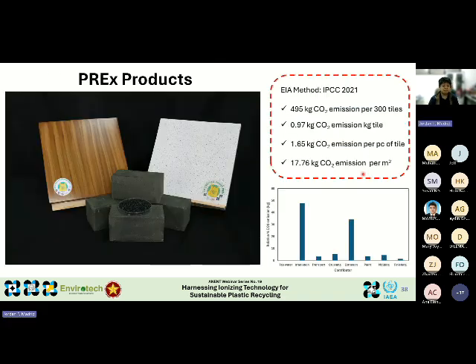The results of our simple gate-to-gate life cycle assessment showed that producing Prex tiles leads to an emission of around 17 kilograms of carbon dioxide per square meter of product. To put this number into perspective, this value falls roughly in between the reported figures for conventional ceramic tiles, which are reported in published data to emit around 15 to 16 to 25 kilograms of carbon dioxide per square meter of ceramic tiles.